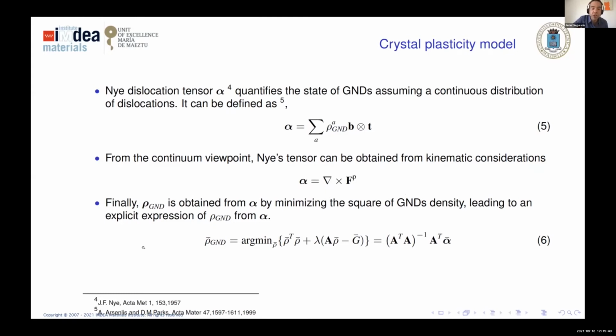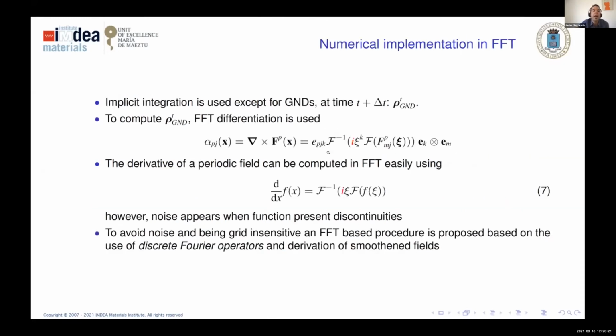How do we do that? We do a minimization. We want to find the dislocation density of GNDs in each of the systems we consider, 12 in the case of FCC, that minimizes the number of dislocations, because the Nye tensor has 9 components and the density of GNDs has 12. So there are infinite solutions of GND density that give me the same 9. With this minimization procedure proposed by Arsenlis and Parks, we can get a direct relation. So we do that, and how do we solve this?